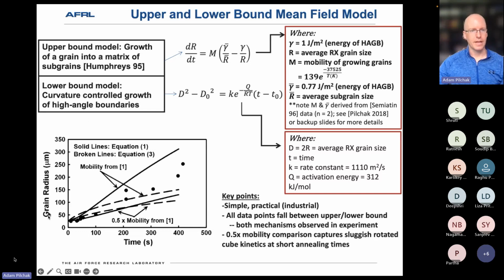So we just plotted our data, grain radius versus time, along with these two models, and some of the model parameters were actually taken from prior work that Lee Semiatin had done on a variety of different Ti-6-4 rods or bar stock with intentionally different textures to try to tease out the role of texture on grain growth kinetics. Having access to that data allowed us to estimate the mobility and the energy of the high angle grain boundaries, and allowed us to make these estimations. And as you see, the data points fall between both of these upper and lower bound models. That's not incredibly satisfying. It'd be a whole lot nicer if we could have merged these two together, but we didn't quite get there. But at least it's a sanity check showing that the data points are falling within the mechanisms that we believe to be controlling the behavior.